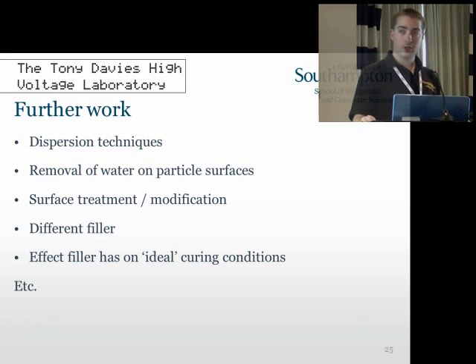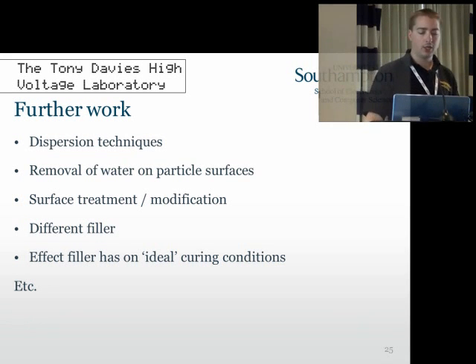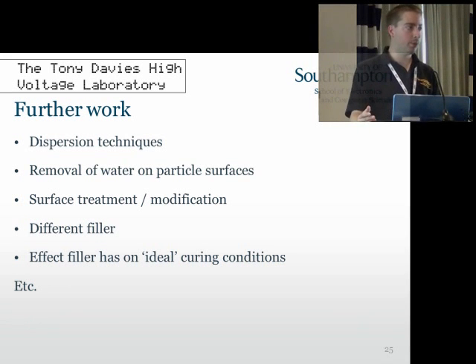There's a lot of further work that obviously can be done here. Looking at different dispersion techniques would be one, to see how easily we could get this 5% dispersed so that there's no negative effect, or whether that's even possible at all. Removal of water from the particle surface. Obviously you're going to have to bake your filler to try and get the water out. And also any kind of surface treatment modification.